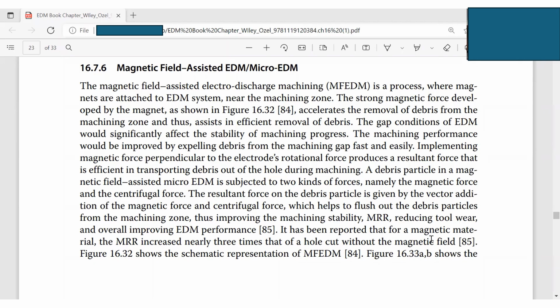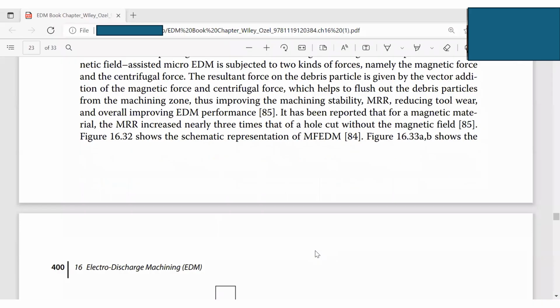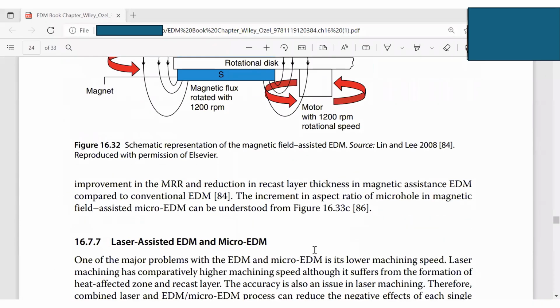So this has been reported for magnetic material. The MRR increased nearly 3 times that of the process without magnetic material. So this is a very, very effective way to drill holes. Figure 16.33 A and B show the improvement in the MRR and reduction in the recast layer thickness. The increment in aspect ratio of microhole in a magnetic field can be understood from figure 16.33c.